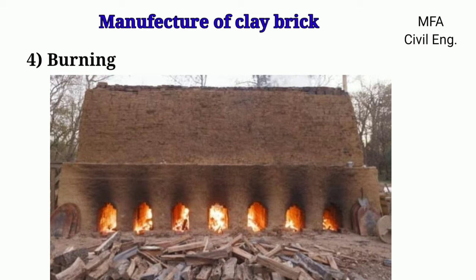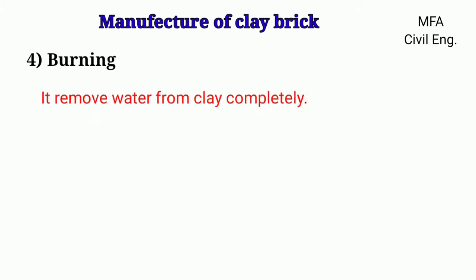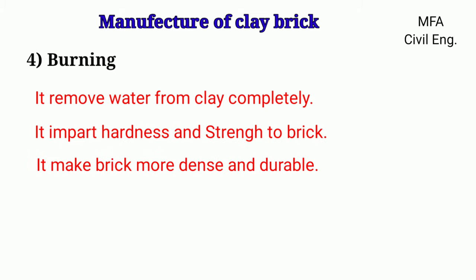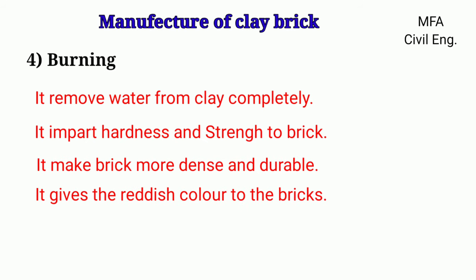Burning is the last and most important operation in the manufacturing process of the brick. Bricks should be burnt properly. Burning is done to remove water from the clay completely, impart hardness and strength to the brick, make the brick more dense and durable, and give a reddish color to the bricks.